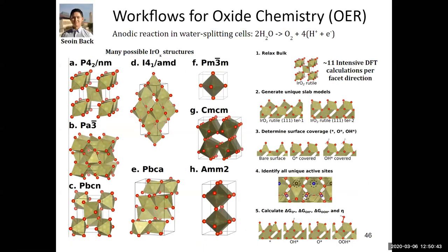Okay. We can do the same thing for oxides. There's another set of challenges for these oxide materials in that there are many different polymorphs, some of which are in the databases like OQMD and Materials Project, some of which have not been considered. And there's an additional challenge in that because they're oxides and we're usually considering oxygen chemistry or there's a bunch of water around, there are a lot of different terminations that you can have also.